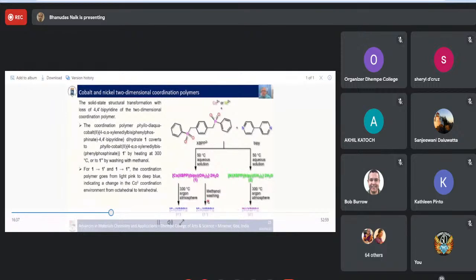Or also with nickel, the same case here, we can form this compound here. But very interestingly, we tried to just remove the bipy ligand, leaving just the water as well. And we have another compound which I called 1 double prime. And this might actually have water molecules bound to the cobalt center. We're not sure, but both of them have the same tetrahedral geometry at the cobalt center. You can see by the color change. Cobalt 2 hexacoordinate is characteristically pink colored, and cobalt 2 with tetrahedral geometry is a dark blue color, and both these compounds are dark blue. The nickel compound is a light green color, and when you remove all the extra ligands, we have a purple colored compound here.